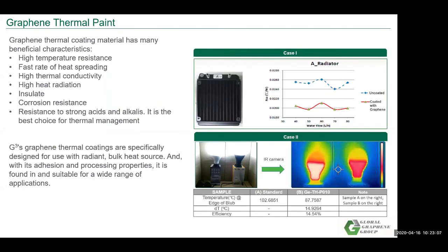And we also put graphene into epoxy resin to develop a product called thermal paint. So this is a very useful solution for any enclosures or heat sinks. You just simply spray or dip coat this product on your enclosures, and you can get better thermal dissipation properties. As you can see in the slides on the right, we sprayed such paint onto the LED light casings, and you can see how effective it is at making the LED light cooler.